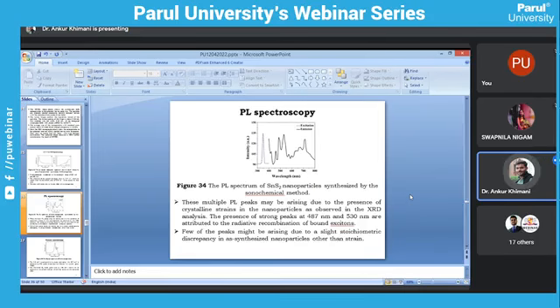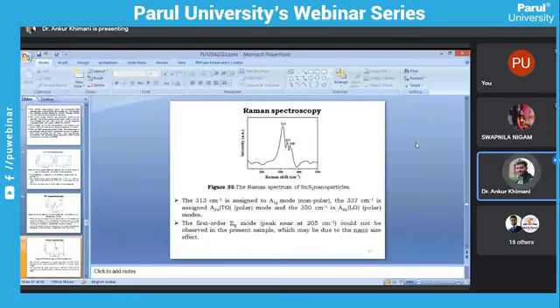The presence of strong peaks at 487 nanometer and 530 nanometer are attributed to the radiative recombination of bound exciton. So this gives information about the exciton. A few of the peaks might be arising due to slight stoichiometric discrepancy in the synthesized nanoparticle, other than strain. Raman spectroscopy. The Raman spectrum of the SnS2 nanoparticle shows three distinct peaks.